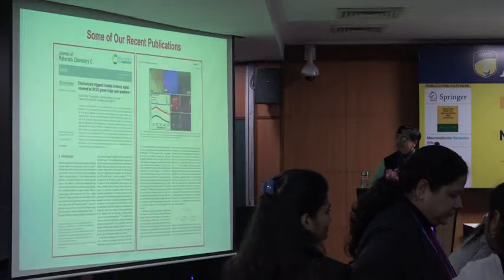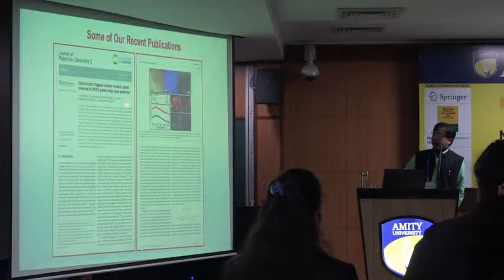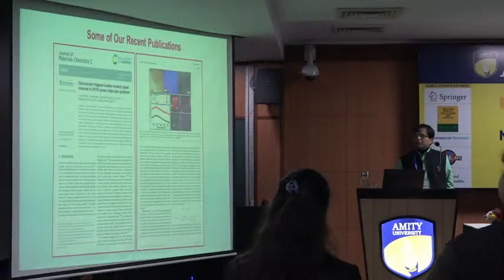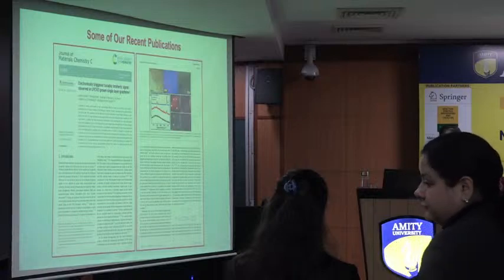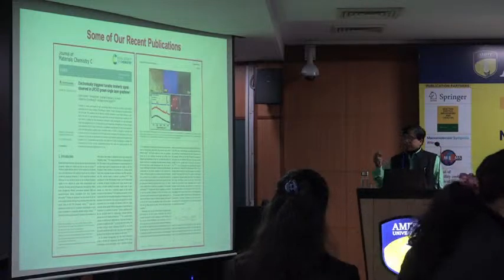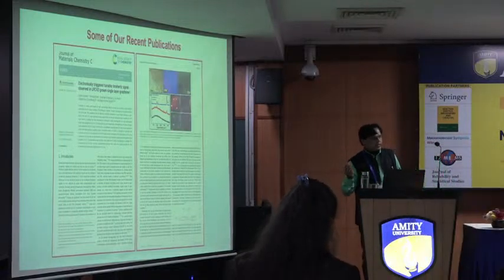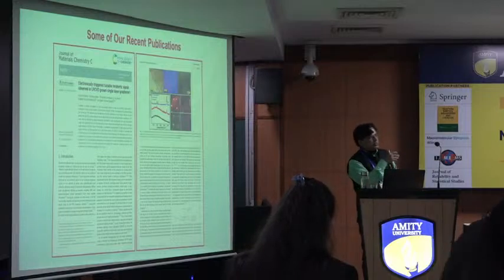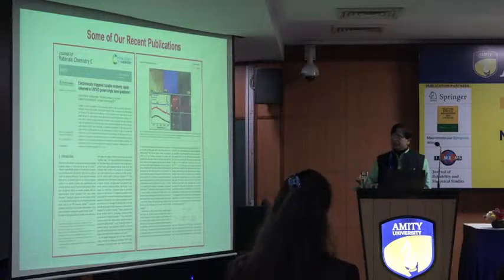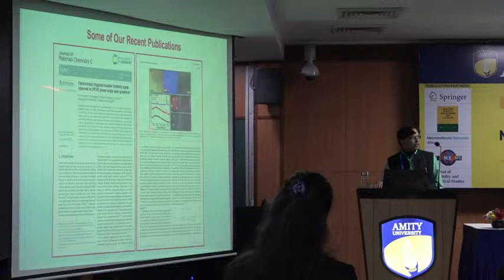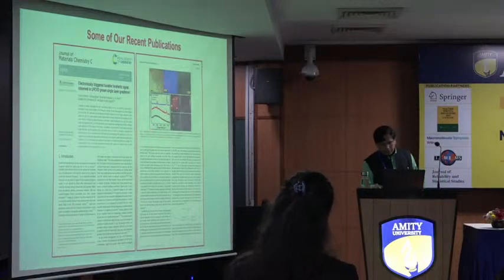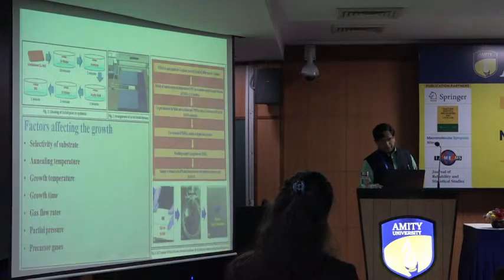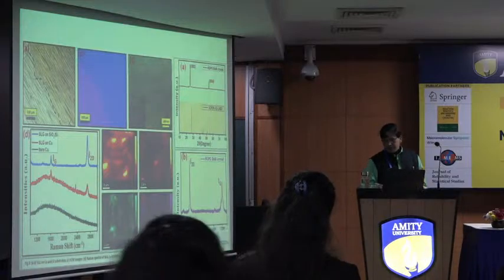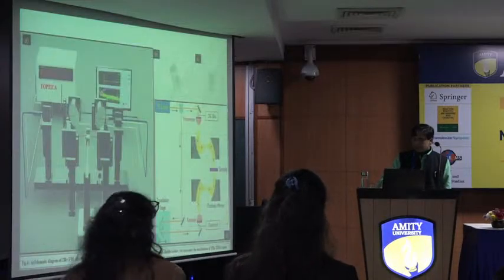And if you see here, we recently reported the electronic tuning of single layer graphene. We are trying to delocalize pi electrons, triggered by the applied voltage, and change the frequency of the terahertz. So for the first time we reported a tunable terahertz frequency using this kind of single layer graphene. This paper was recently published last month.